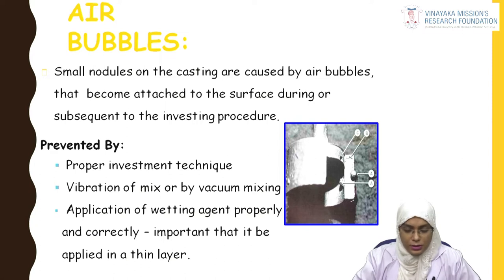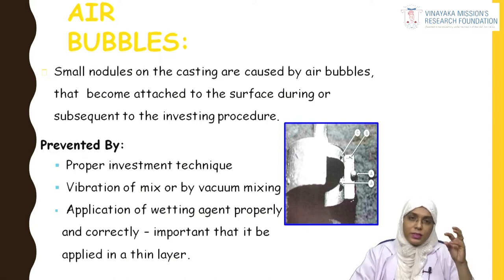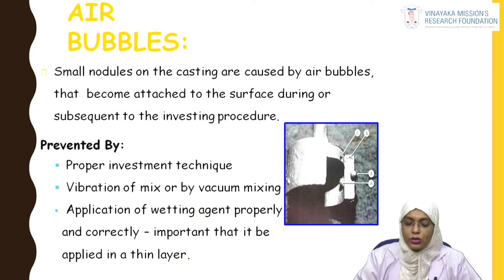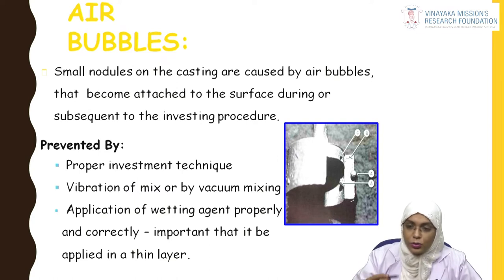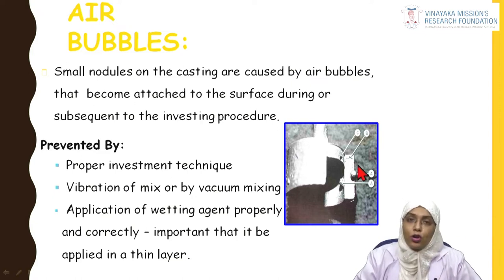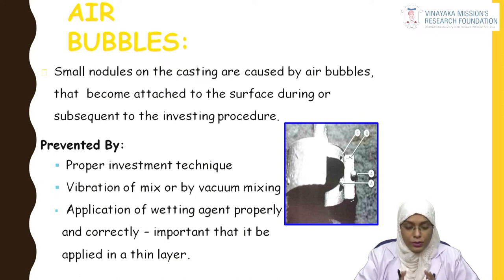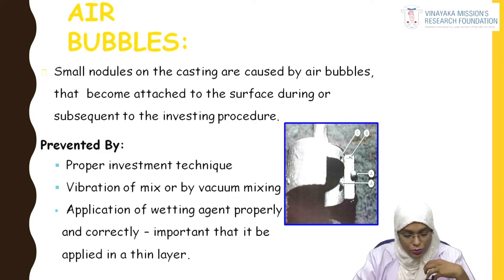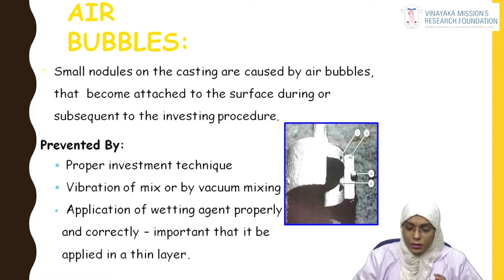The third defect is air bubbles — very small minute nodules on the casting surface, as seen in the picture. These nodules occur because air bubbles attach to the surface during the investment procedure; if vibration is not done properly, those air bubbles are replicated as nodules in the casting. To prevent this, use proper investment technique: apply vibration, do vacuum mixing, and apply the wetting agent properly so there is no air entrapment within the investment.